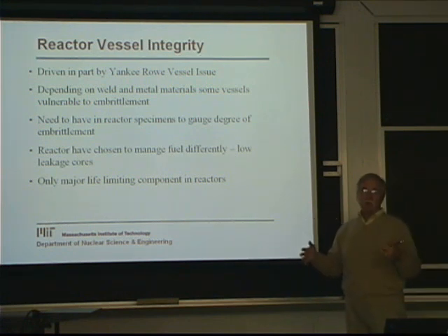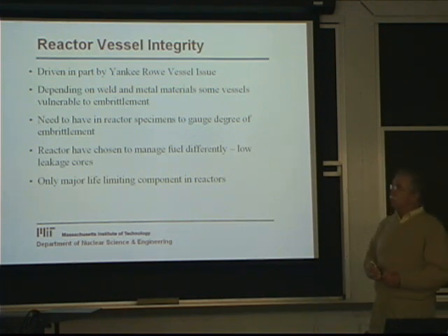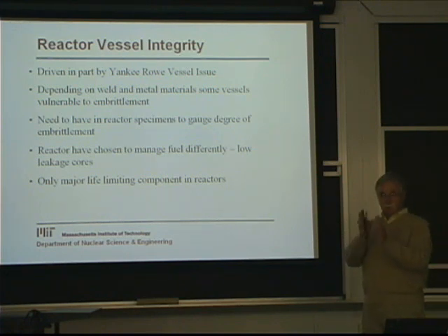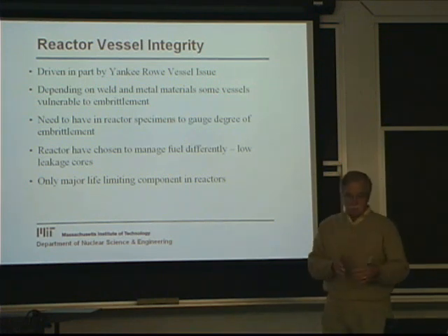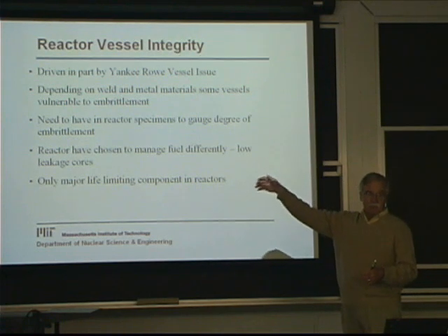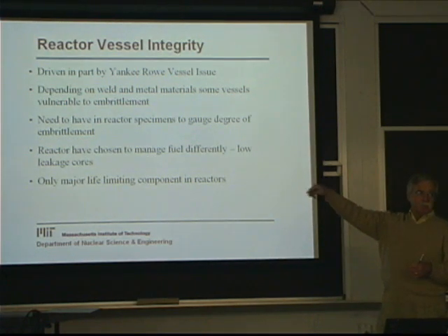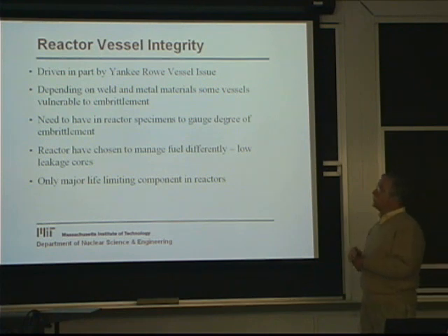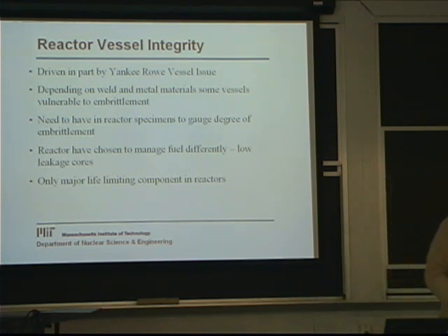In other words, the holders broke, and they were able to retrieve some, and they had a limited amount of data upon which to base predictions. The way they made these predictions was they put them very close to the core, and over a period of time, they would take out specimens and determine what the degree of embrittlement was. At Yankee, we had a number of specimens early in life, and we had one really late in life, and you couldn't really just draw a straight line curve to it. But pretty much all reactors today have these in-core specimens that they use to determine whether or not the vessel is becoming overly embrittled.